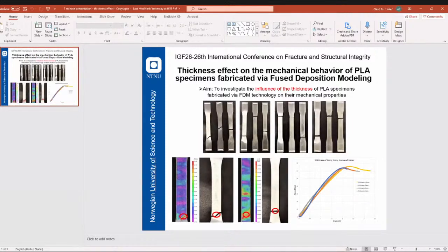I know you haven't done it, but just your guess or based on your experience in this research, do you think the thickness effect would be more or less, and why? I think in that case it would be more, because we have weaker layer bonding if we have a higher thickness for each layer, so the defects will be more dominant compared to the thickness we have now. The more defects we have, the more obvious the thickness effect will be. That's my best guess so far. Of course, it would be nice to see.